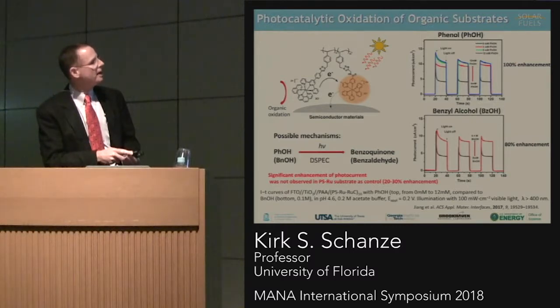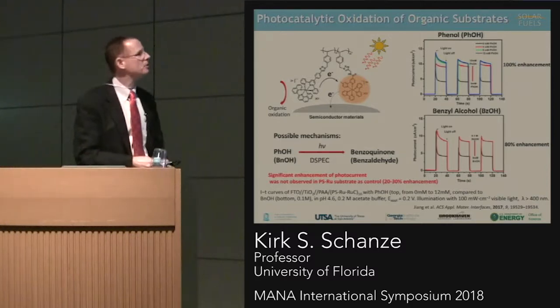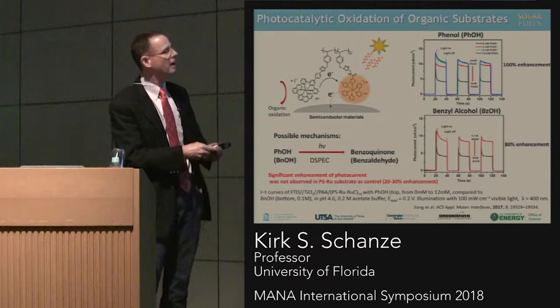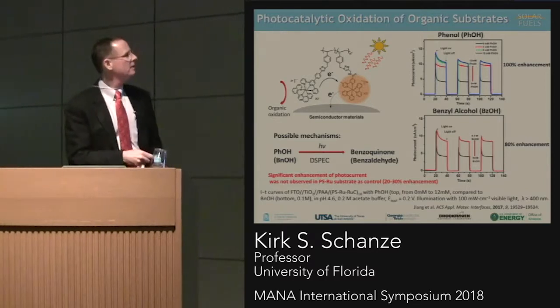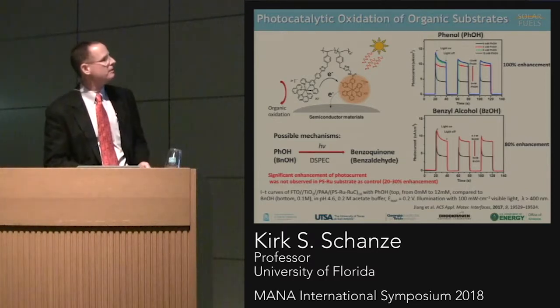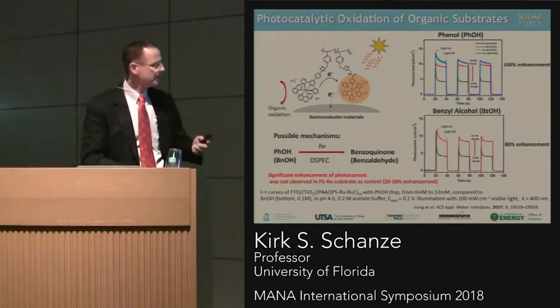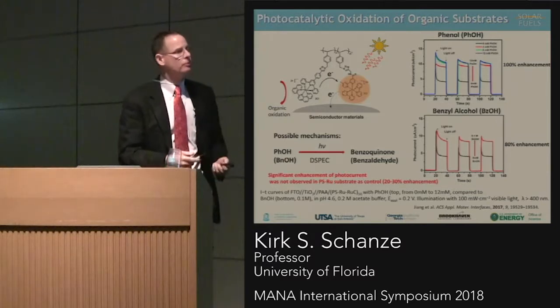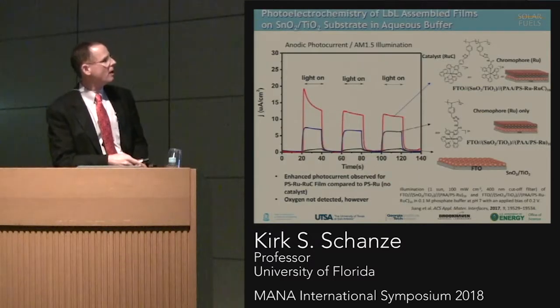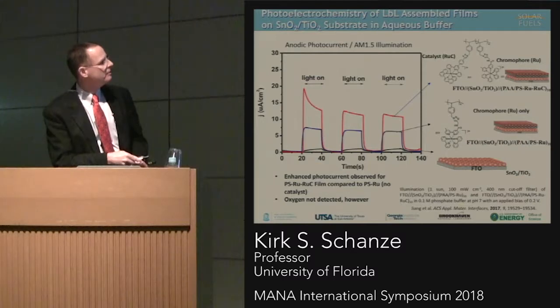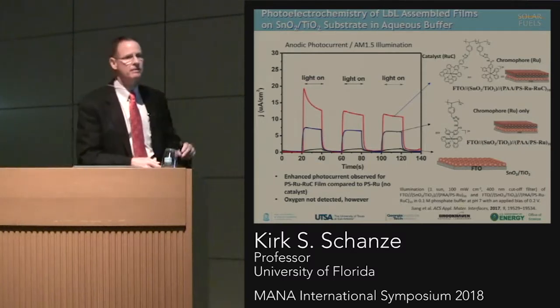And here I show again photocurrent enhancement when we add a sacrificial reagent. So we're able to oxidize organic substrates with this chromophore-catalyst assembly by illumination of the electrodes. But in this case, we actually also believe we are able to carry out water oxidation. And what I show here are photocurrents for two different assemblies. The blue one is an assembly that contains no catalyst.